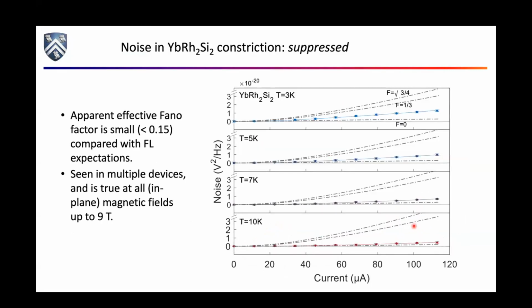All right, so here's the big shot, right? This is the meat of this whole thing. Remember, it's ytterbium rhodium 2 silicon 2. People have studied this. It's a strange metal, linear in T resistivity. Quantum critical charge fluctuations are seen by things like terahertz optical conductivity measurements. There's every reason to believe in all the measurements other people have done in the system that electron-electron interactions are really strong. So if electron-electron interactions are really strong and phonons aren't really important, which is what all the other measurements imply, conventionally, if it was a Fermi liquid, you'd expect to see √3/4 as your Fano factor. You do not.